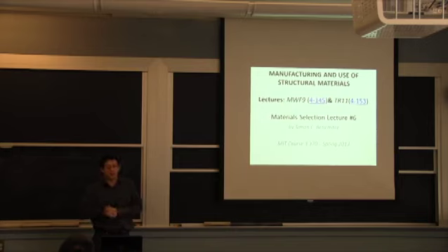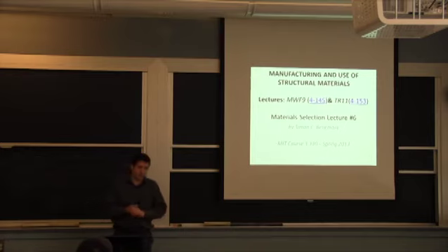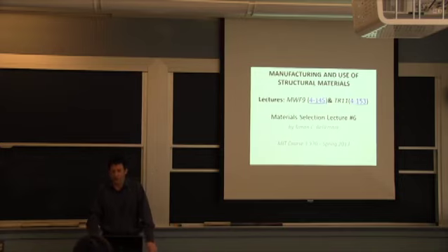We talked about 2 mils per year of degradation, but that varies from almost zero to higher values, depending on the local environment. As you go below the water table, it tends to be more constant because it's a homogeneous environment. But right between the water table and the dry soil is an area where there's a lot of fluctuation. And I've seen that as well on underground storage tanks for gasoline or oil, where the top looks pristine, but the bottom has a lot of damage.